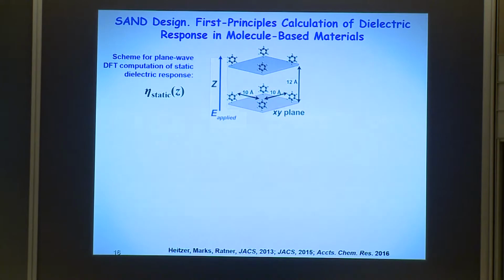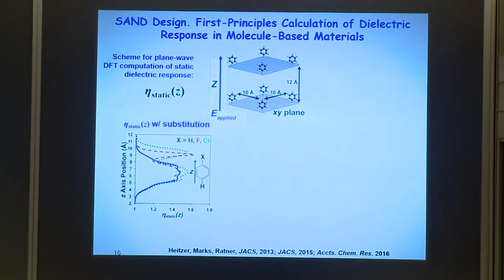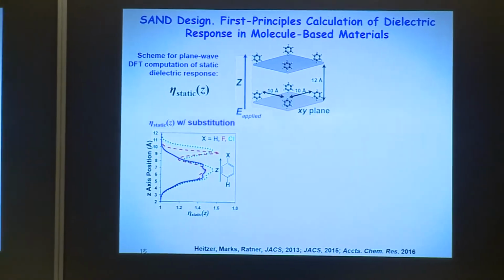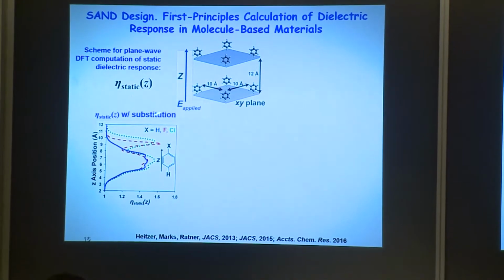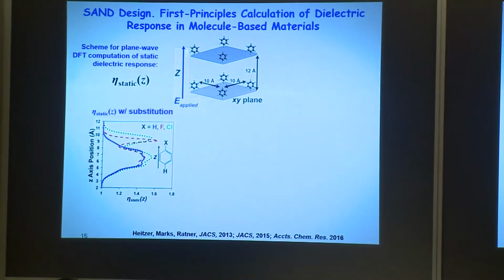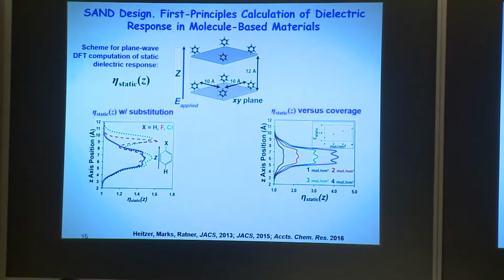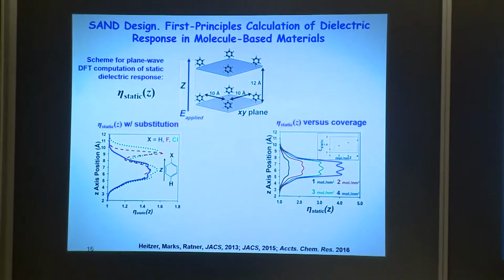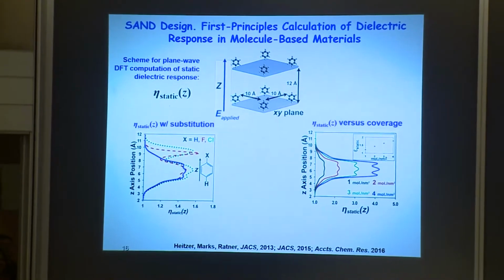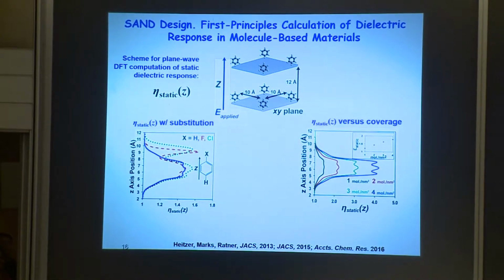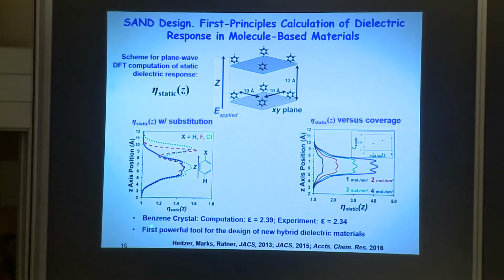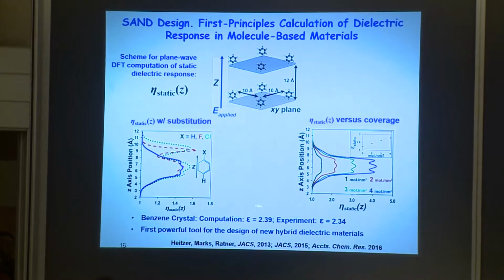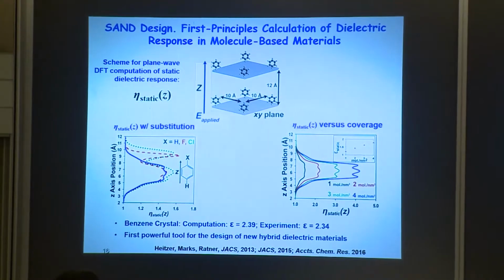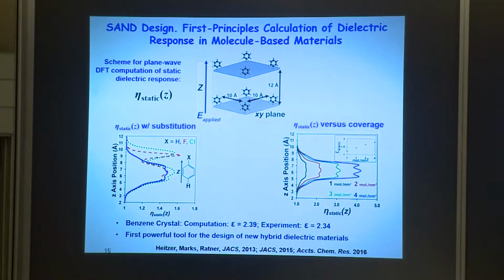And it works. So we said, well, start with a layer of benzene molecules. This isn't a sand dielectric yet, but calculate the dielectric constant. It's a plane wave periodic DFT calculation. And here are some organic molecules, for example chloro- and fluorobenzene, and you can actually calculate the dielectric constant profile along this direction. Now, you can vary the coverage of the molecules. You can push them closer together, pack them, and get these. At this point, we said to Henry, well, is there a connection with reality here? So he took the benzene crystal structure from the literature and computed the dielectric constant. This is the number he got, and this is the experimental number in the literature. So it's a very powerful tool for designing gate dielectrics.